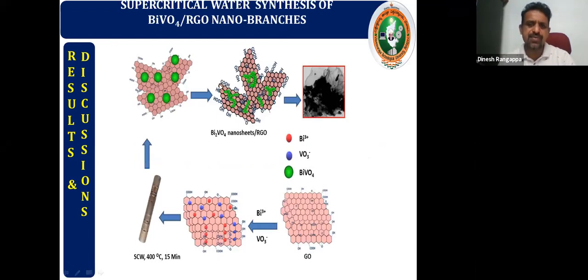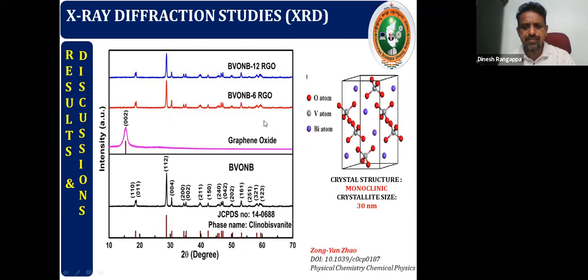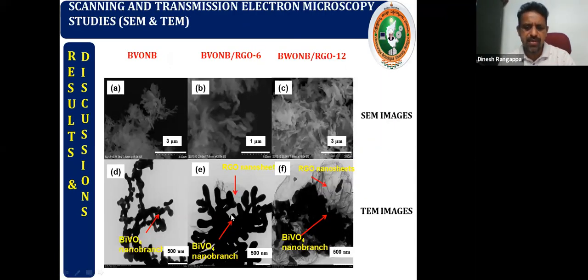when mixed with RGO, it forms a heterostructure with RGO. So we could obtain the pure bismuth vanadate nano branches, and you can see the monoclinic structure of bismuth vanadate, which matches with JCPDS 14-0688 phase, and the crystallite size is about 30 nanometer. And here you can see nano branches coated on the graphene RGO sheet.